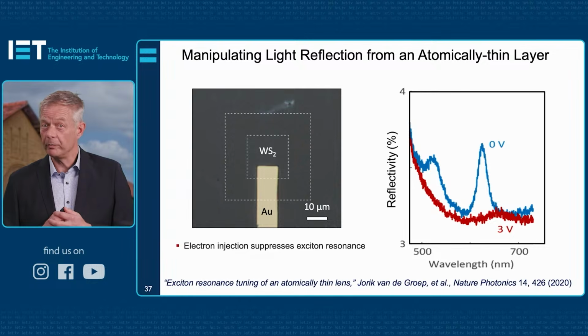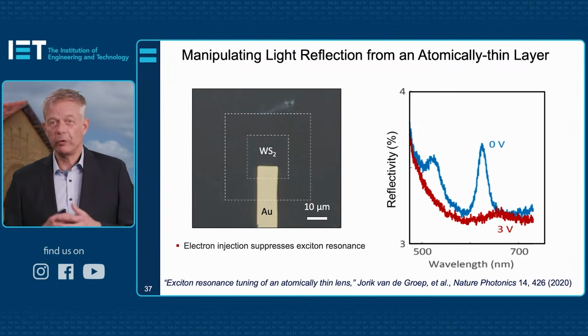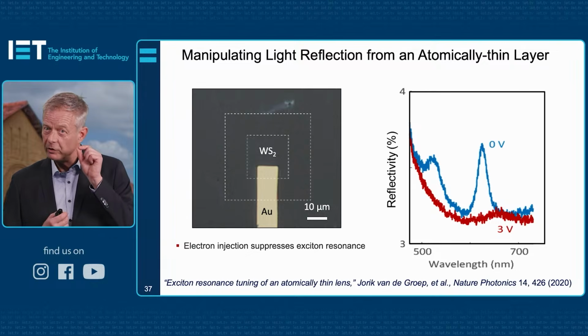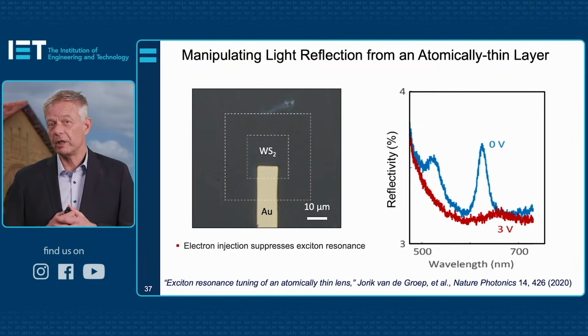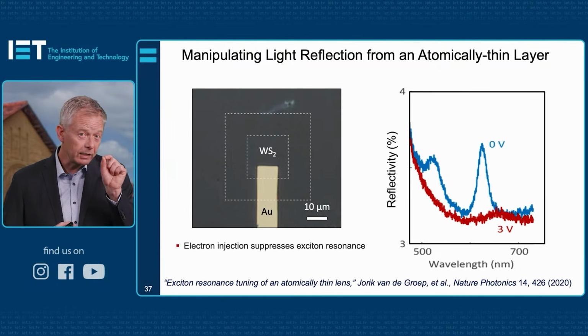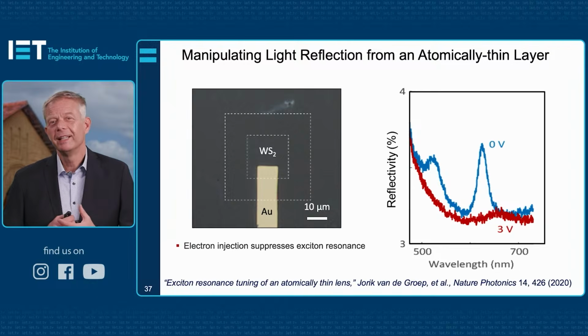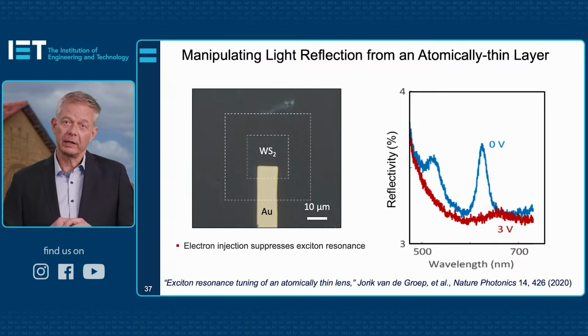And indeed, even at room temperature, if you look at the reflection, here the reflectivity is maybe 3 to 4%, so not as amazing as at 4 Kelvin, but we see two very strong resonances in the blue curve if we don't apply any voltage. If we inject a little bit of charge, similar to the experiment by ETH and Harvard, the resonances completely disappear. This was amazing to me, since never before could we completely turn off resonances of metal nanoparticles or semiconductors.